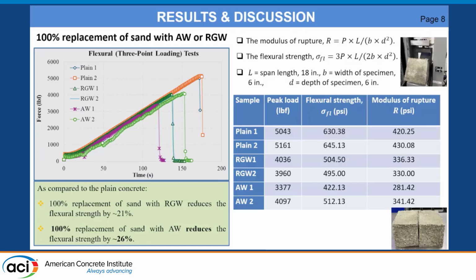got to about, the modulus of rupture there is about 420, 430. With the recycled glass, you can see we're sitting right about 330, so a little bit further down. And the alumina waste was between 281 and 340.